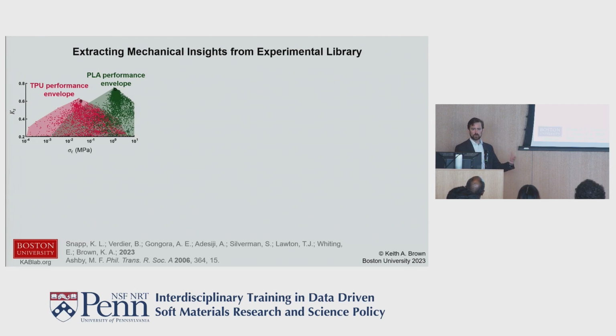And we can zoom in on this and say, some other classic things you could do from a materials perspective. You could build an Ashby plot, looking at, for example, the relative yield stress or the relative strength of the material versus the relative density. You typically see that less density, these sparser parts, end up being less strong. And you could look at the power law here. This tells you our power law is about 1.36. So the properties are giving us something between the buckling regime and the stretching regime. So it's what we would expect for these kinds of structures.